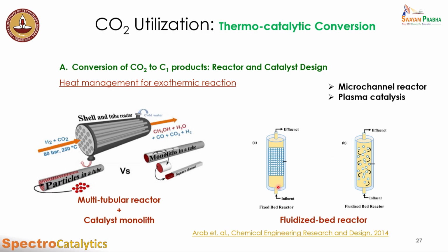Another mechanism is the fluidized bed reactor. Here, instead of a fixed catalyst bed, our catalyst particles are in fluidized motion, and because of that, heat dissipation is more efficient compared to a fixed bed. But the issue is that there is a wide distribution of residence time of the reactants inside the reactor because of the fluidization, which detrimentally affects the product distribution at the end.